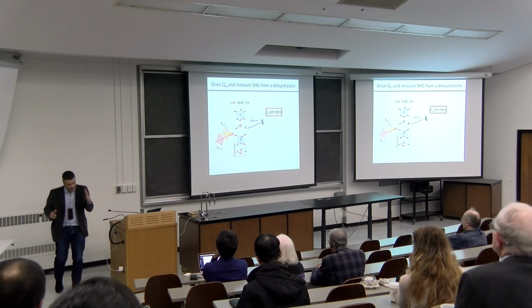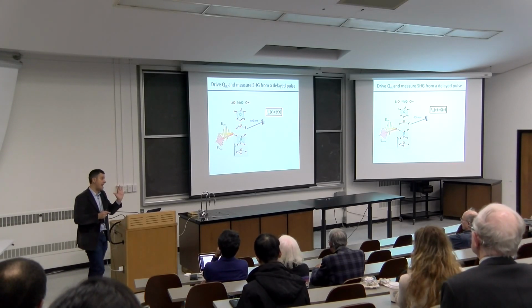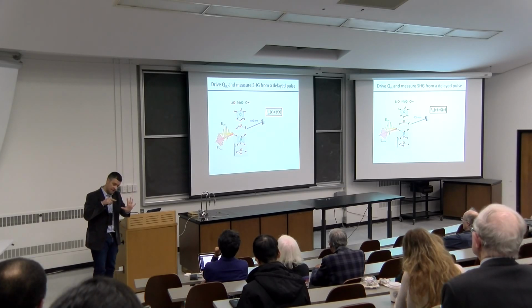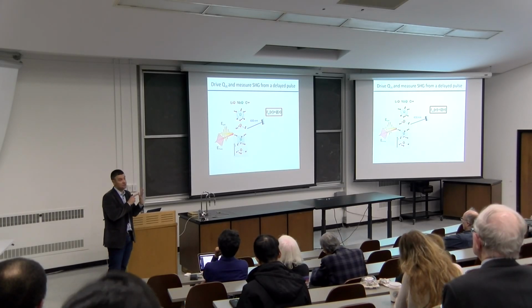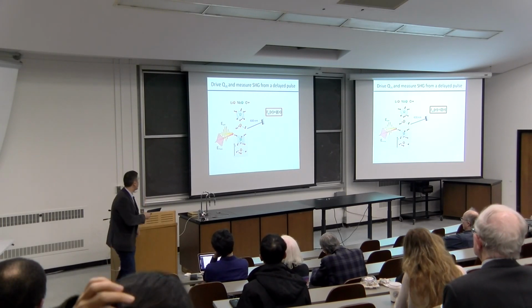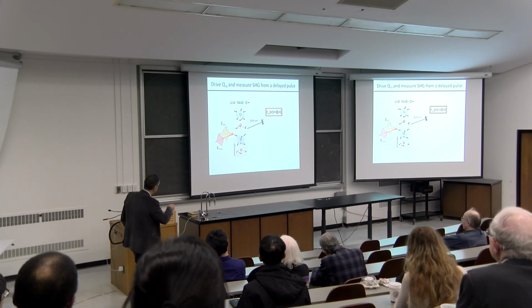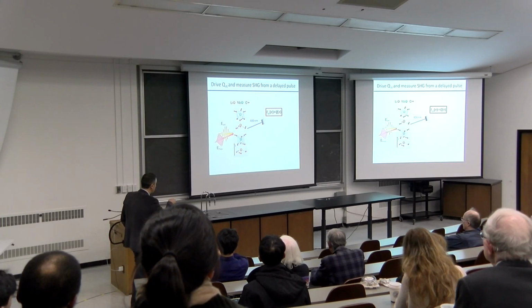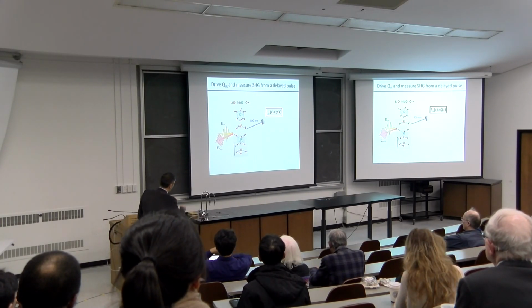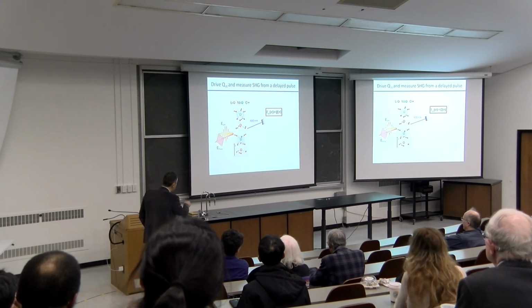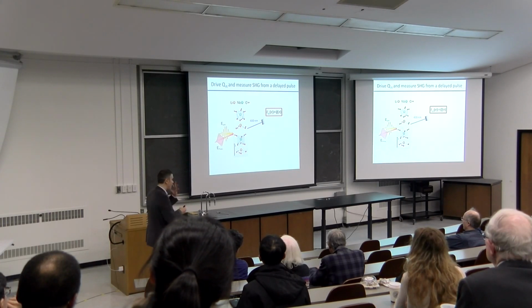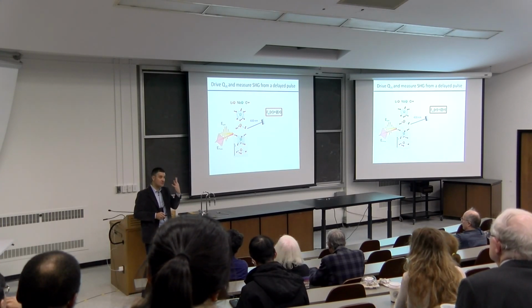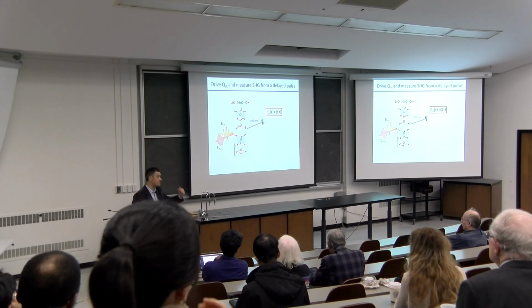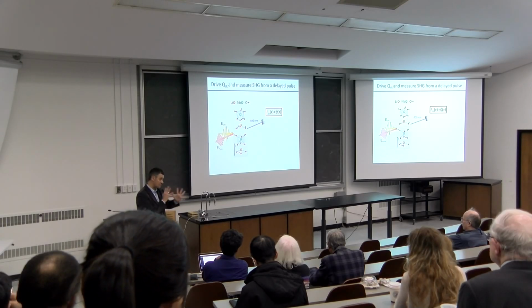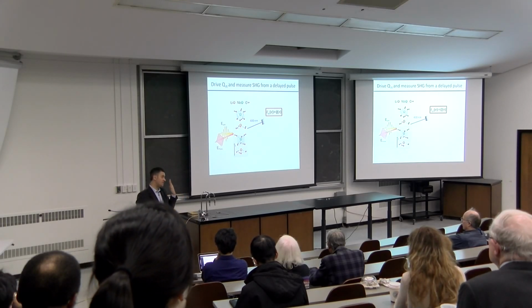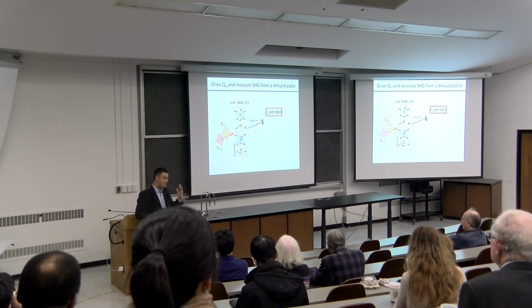So what I want to do is to drive a mode to very large amplitudes and then have a means to study the response of the system as a function of time. Of course, what I would like to do is to have an X-ray pulse that can be made synchronous not only to the drive. This is my pump pulse, which drives a specific high-frequency phonon of the system. And what I need, I need to do a couple of things. What I would like to have is a pulse in which the absolute phase of the mid-infrared light is in register with its envelope. I want the absolute phase not to change because the way these experiments are done is by doing the experiment many times and repeating and changing the delay between multiple pulses and studying the response. What I want to do is to push the phonon to the right or to the left at every pulse always at the same time.